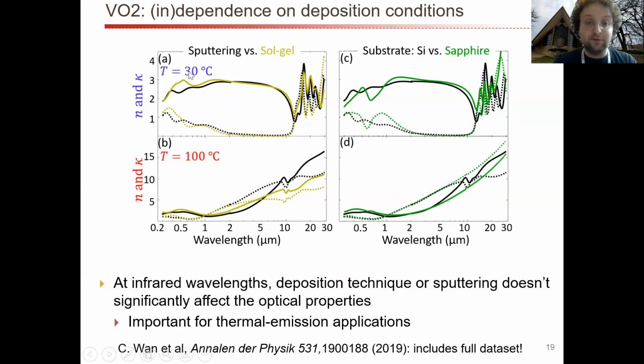If you look over here below about 1 or 2 microns, so kind of in the near infrared and the visible, you'll see that every time you deposit a film, it's quite different because the electronic structure, the band structure, depends very strongly, again, on the deposition conditions. And so you really have to characterize your film every time before you do some simulations.